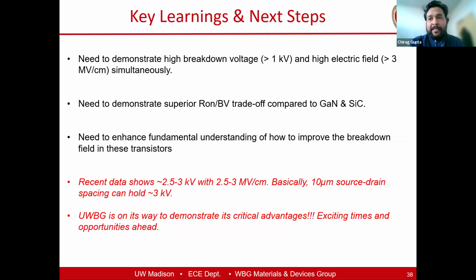The way I think about this is that the reason why we are doing it on sapphire, not on silicon carbide, is just because we are more familiar with sapphire, and sapphire is cheaper to do. But if thermal conductivity is a concern and you really want to use gallium nitride for high voltage application, one possible solution is to use GaN on silicon carbide, because then you can take advantage of silicon carbide thermal conductivity and go to high current, high voltage applications.